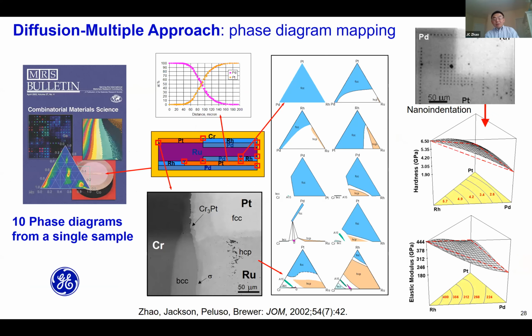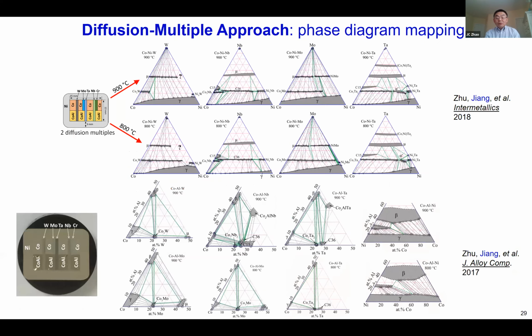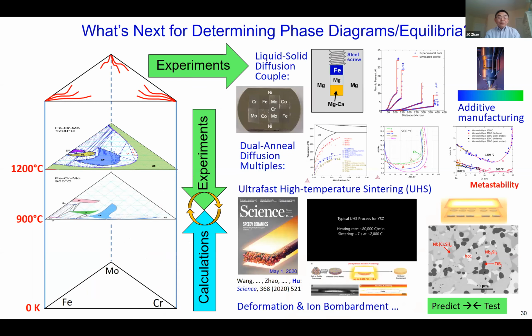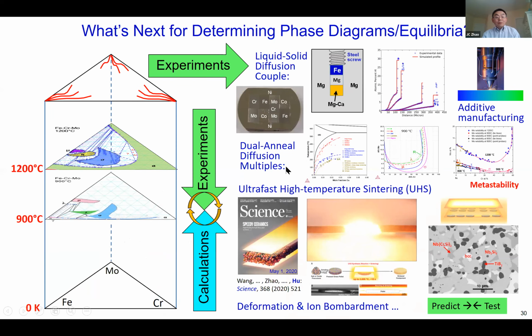Phase diagram, I already talked about this many times, and I'm basically going to say we can build many multiples and get many phase diagrams into one sample very efficiently. We have done multiple ones, like this in collaboration with Liang Jiang, measuring cobalt-based superalloy related systems. You can see, from one sample, we got a large number of ternary systems. So in the future, the work we will be doing is to measure experimentally. It's very easy to measure high temperature ones, right? The low temperature diffusion coefficient is so slow, it's very hard to measure.